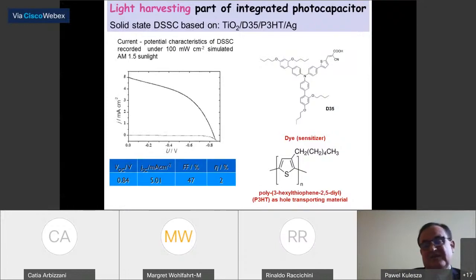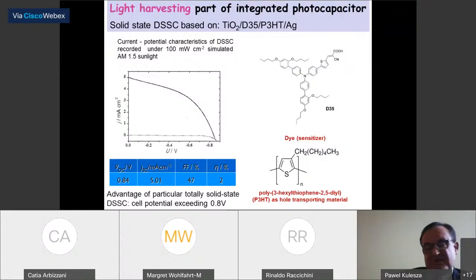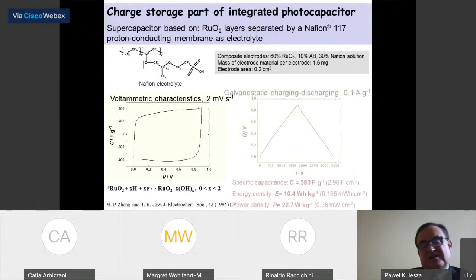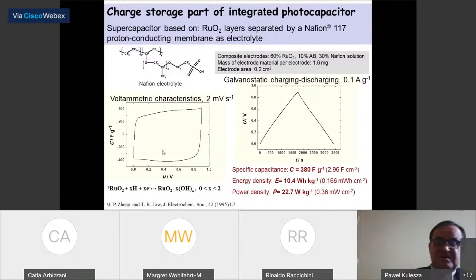So if I look at the dye-sensitized solar part, we use a relatively not very efficient photocell, but we use a completely solid system with a conducting polymer, which is a hole conducting system. It's not as efficient as the iodine couple or nickel hexacyanoferrate, but it works in solid state. And on the capacitor or pseudo-capacitor part, we use a ruthenium oxide system, which is a very effective system, it's well known. And combining a less effective system with a very effective system sometimes works in favor of both.